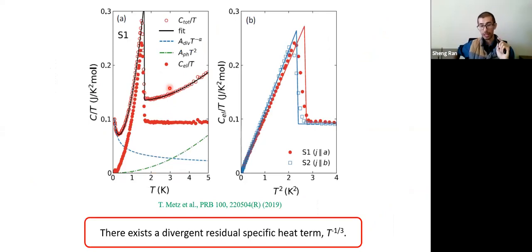So we measured the specific heat down to even lower temperature. This is down to about 80 milliK. It turns out there's an upturn at a very low temperature.